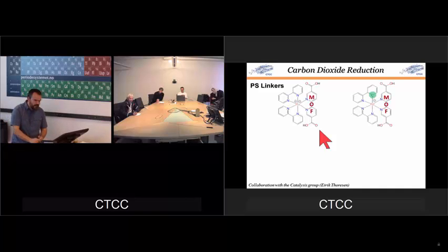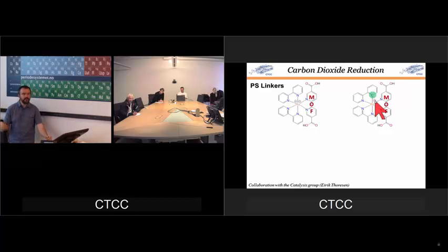And then he tried variations of this. The first thing we tried is to replace this nitrogen here by an anionic carbon, so that overall we now have a 1+ molecule, not a 2+. We hope with this that the HOMO energy will rise, that the LUMO will go down, so that we redshift the absorption, which is what we want, low energy absorption. UV and near UV absorption is always a bit risky, it can trigger decomposition processes, and that's not what we want, of course.